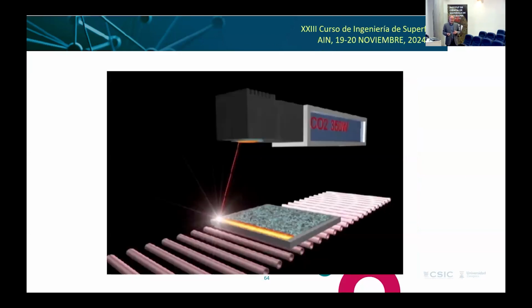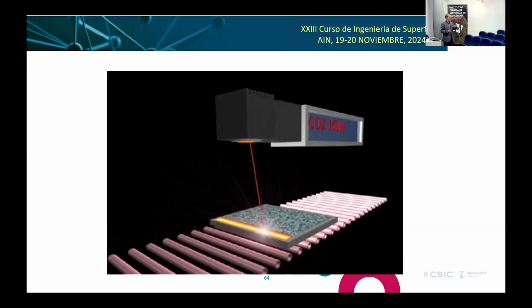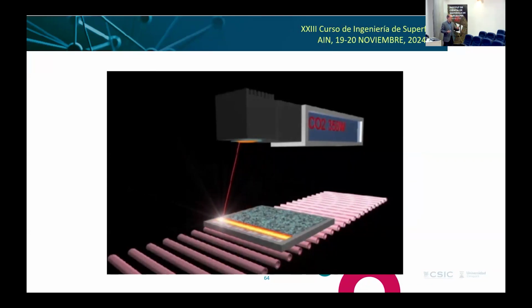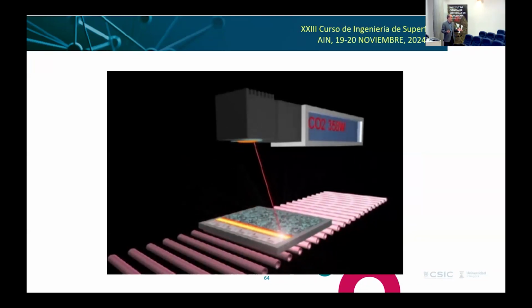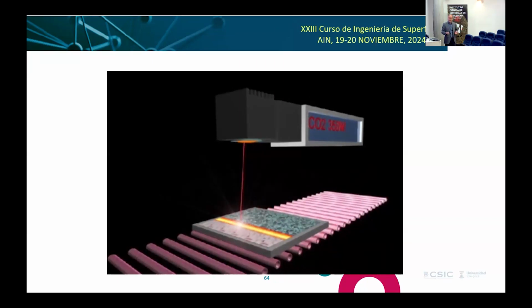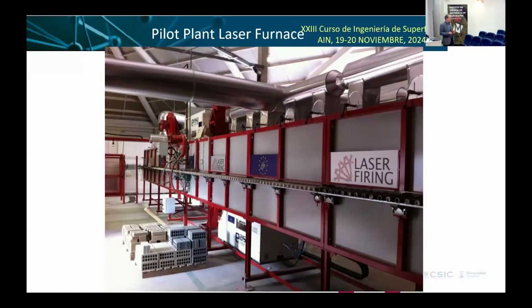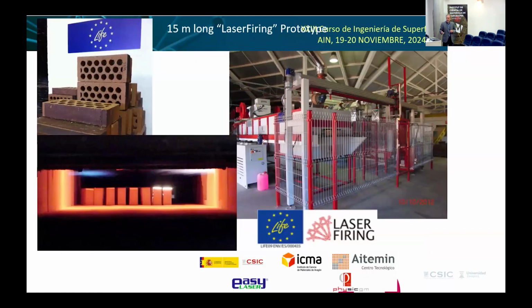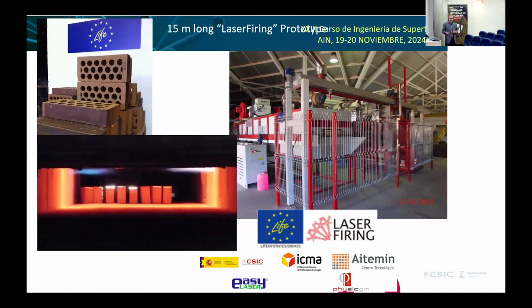And then, so this is what it is. With scanners, we could make a very nice line, and we could apply it inside the furnace onto a moving sample of ceramics and glass, and then we could avoid this thermomechanical stress and avoid breaking. So this is the first nice large prototype we made. It was 15 meters long. It was heated by gas, and it had one laser on top, one laser on bottom, and we treated brick on 4 sides, as you see here.